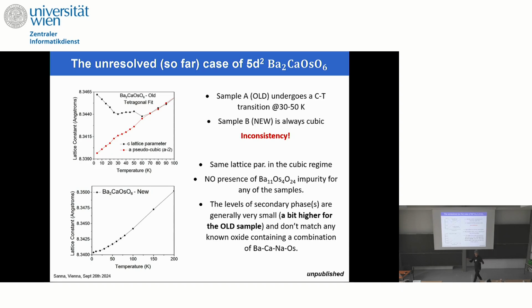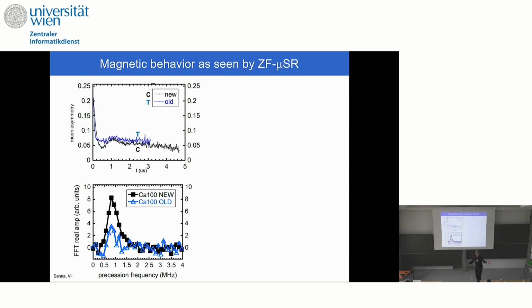Whatever the origin of this, we are now most interested in understanding the nature of the magnetic state in the tetragonal phase and in the cubic phase, from the experimental point of view. Unfortunately, we cannot do NMR. We are now preparing a sample with a 43 enriched calcium isotope, because the natural abundant calcium isotope is not NMR active, so we cannot do NMR at the moment on the full calcium sample, but μSR can be done. You can see that the system which is cubic has a much more pronounced oscillation, while the spectral weight of the oscillating part in the tetragonal sample is lower.